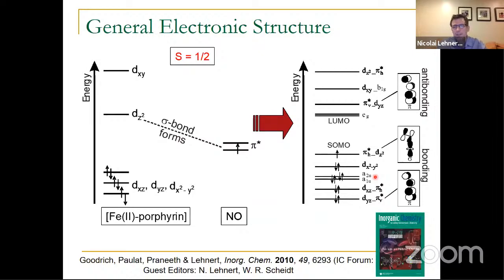So then we can take a look at the principal bonding scheme between an iron porphyrin and NO. And this is very, very crude, but it kind of shows what's going on. So in these kinds of complexes, iron is in the iron(II) state, it's in the low spin state, which means that the T2G type orbitals are here fully occupied, the other ones are empty. And then here's our NO, and NO, of course, is a radical. It has one unpaired electron. And when the NO approaches the iron center, you will start forming the sigma bond between the DZ square orbital of iron and this pi star orbital of the NO ligand, right?